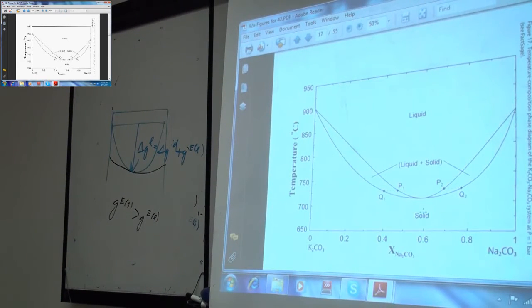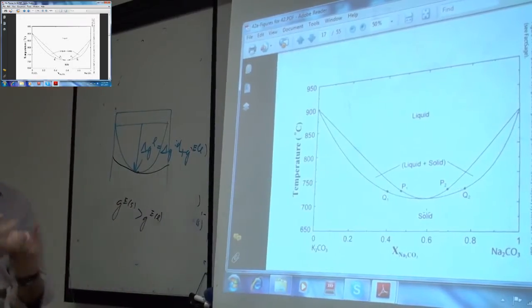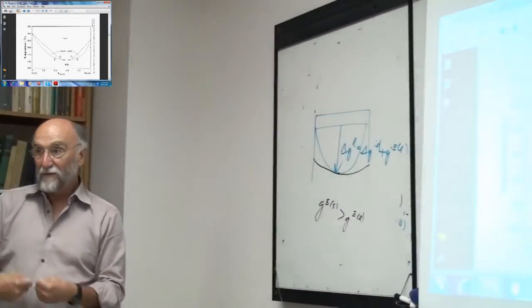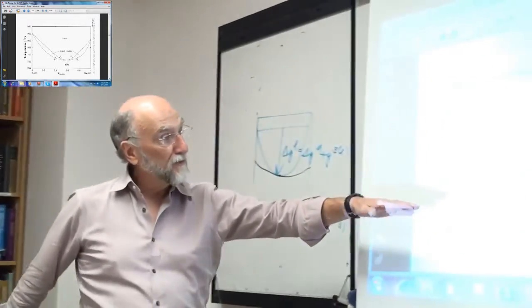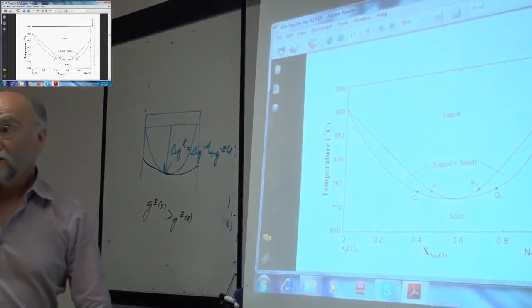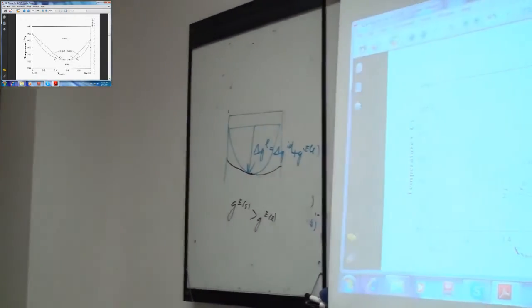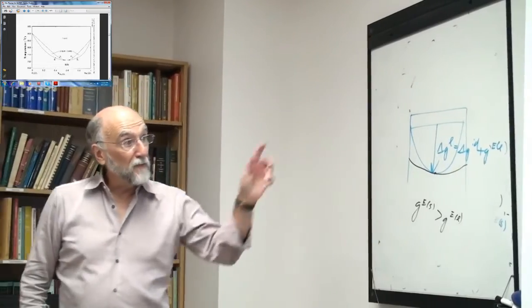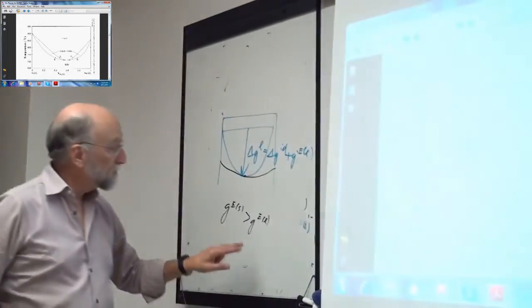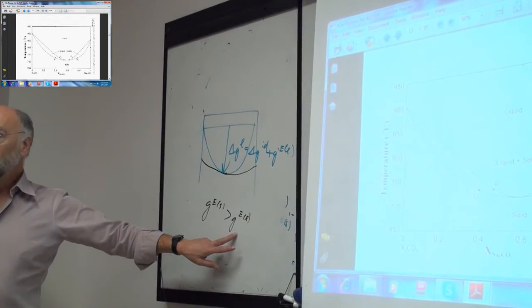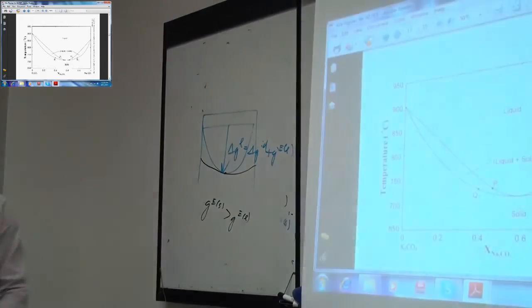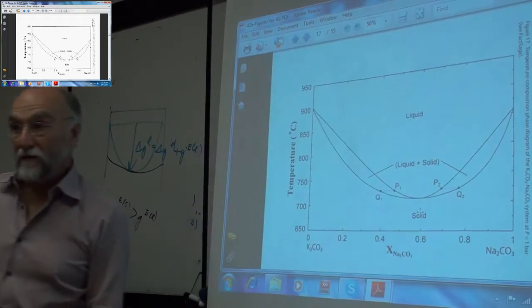If the liquid doesn't want to mix, GXS is positive, which means the A's and B's have a tendency not to want to go together. By the regular solution theory, A and B bonds are weak. In the liquid, they can sort of accommodate themselves around, but in the solid, it's harder to fit everything in. So if the solid has positive deviations, the liquid tends to have less positive deviations. That's why you generally get a minimum, because this phase has been destabilized relative to this phase through the excess properties. The greater the difference, the lower the minimum. As this difference becomes greater, the minimum is pushed down even further.